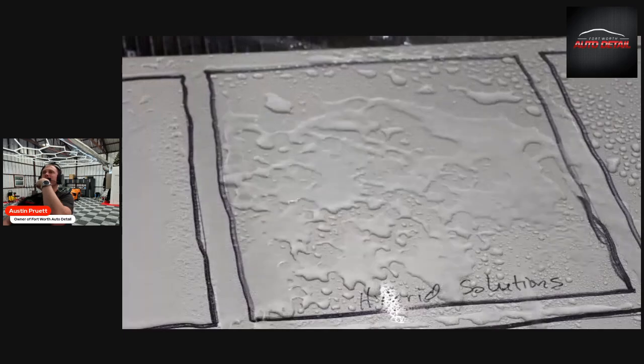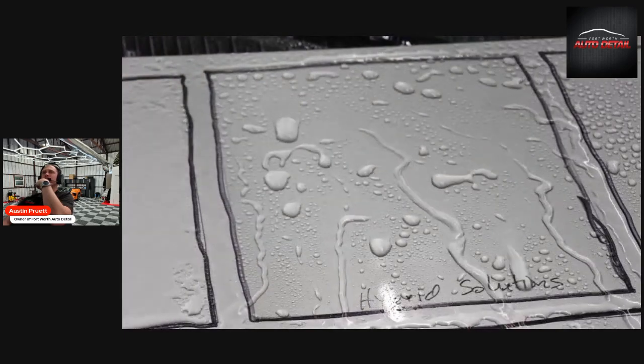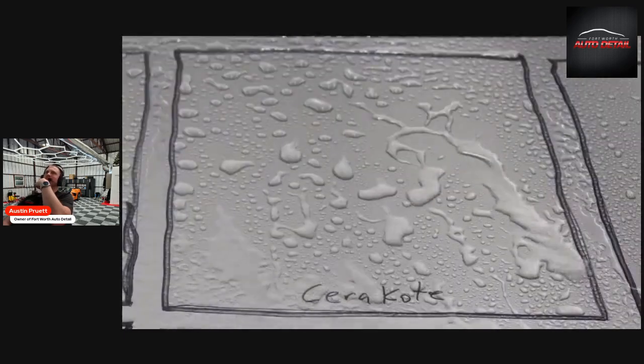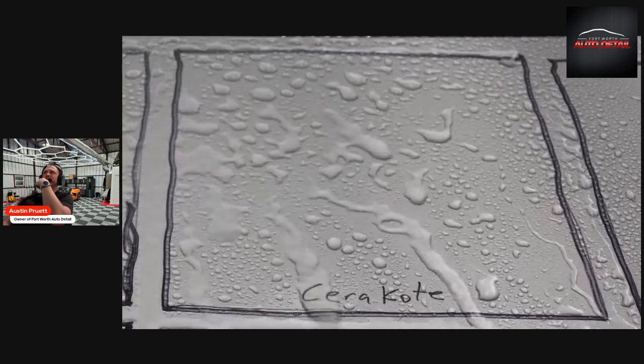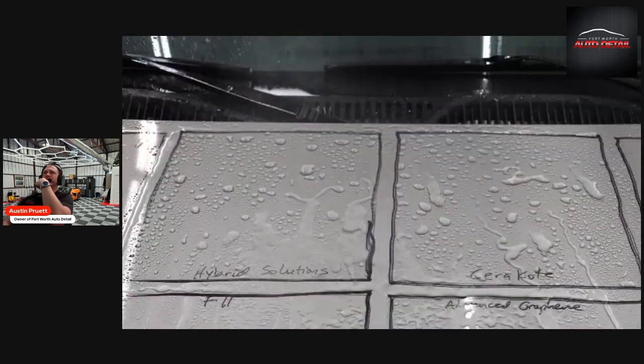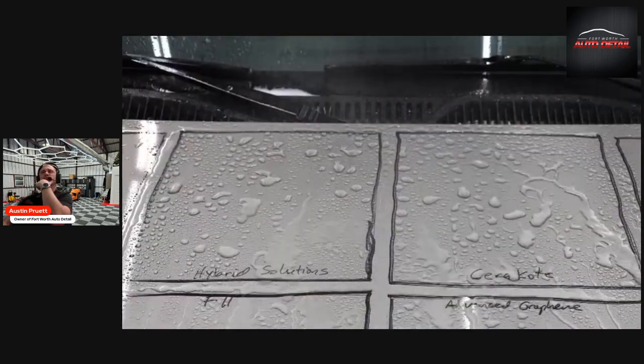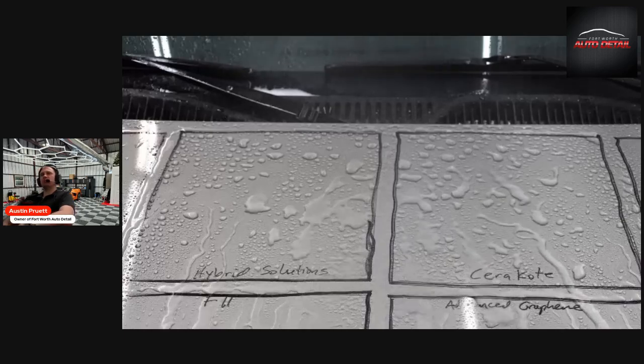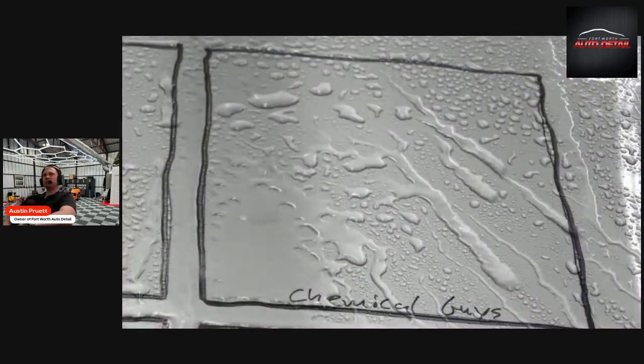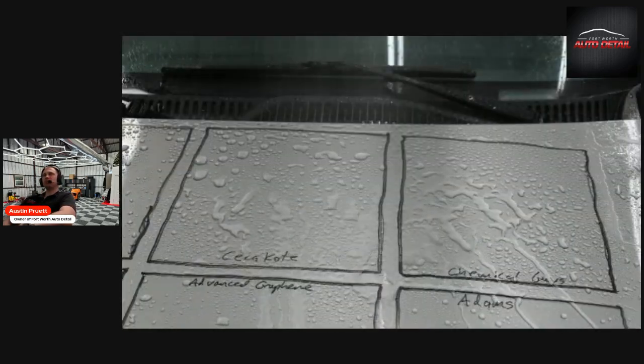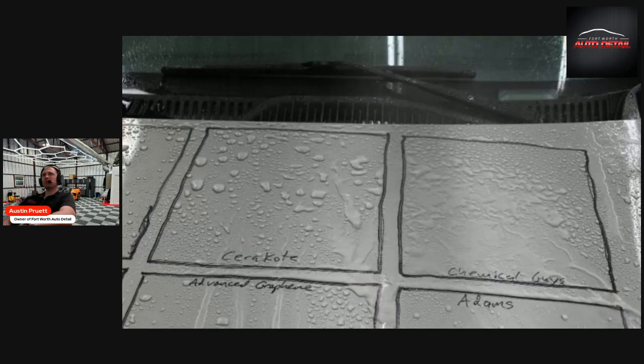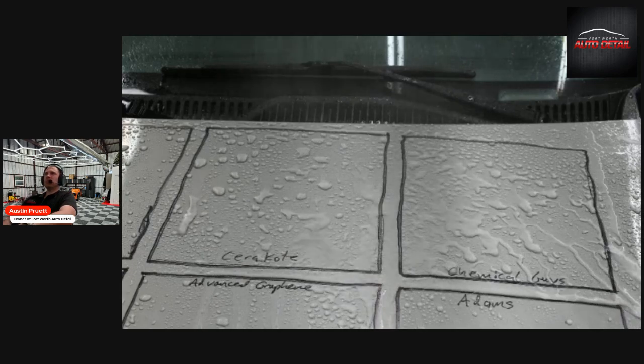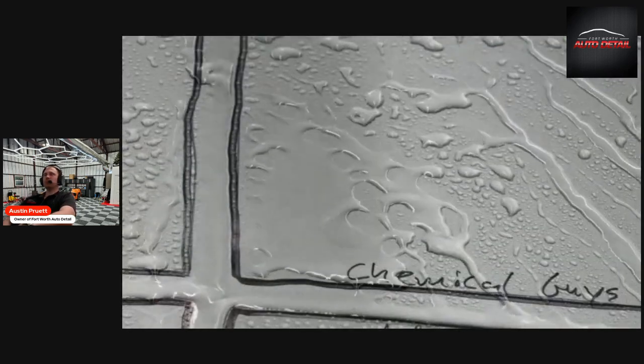Even after the strip wash, the Hybrid Solutions continues to demonstrate excellent hydrophobic qualities. And the Cerakote is also performing very well after exposure to the strip wash. Comparing Hybrid Solutions to Cerakote, they both look about the same and are performing very well. Water is also beading very nicely with the Chemical Guys. Comparing the Cerakote to the Chemical Guys, Cerakote is doing a little bit better with the water forming a tighter bead. And water is beginning to form a sheet on the Chemical Guys.